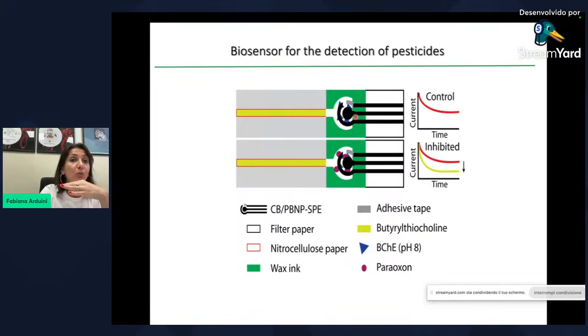This is the strip that we conceived. So the device is constituted of two strips. The first one is for detection of the initial enzymatic activity. The second one is for the measurement of the residual enzymatic activity due to addition of the sample. And in this case, we need to add the enzymatic substrate. And in order to deliver a reagent-free device, we preloaded the enzymatic substrate, in this case butyrylthiocholine, in the yellow strip, so in nitrocellulose paper. And the blue triangle is the enzyme.